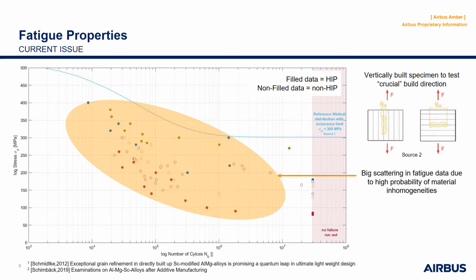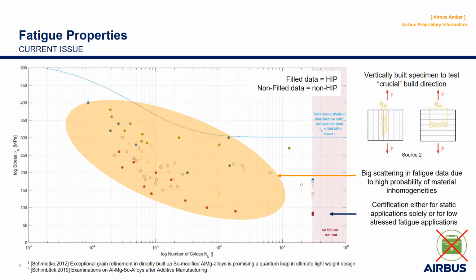So the issue arising with this scattering is the following: certification can either be only for static loads or for an endurance limit of way below the potential of the material system. In this case, for example, 80 megapascal. But the potential of our material system is up to 300 megapascal, published already in the early stage of our research. Most recently, with perfectly adjusted process parameters, even 360 megapascal were obtained and will be published soon. So, unfortunately, everything else below this 300 megapascal endurance limit is killing the business case for this material process combination. So the evaluation of the defects in detail is crucial.